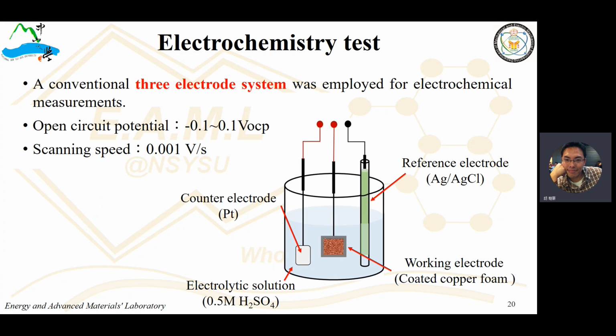Okay. And then we use the three-electrode system to measure its anti-corrosion ability. Okay, so the working electrode is the copper coated with the polysilazane pre-ceramic precursor incorporated with the fluorinated resin or other things and so on. And the counter electrode is platinum, and the reference electrode is silver chloride. And we use 0.5 molar sulfuric acid. Okay, we have a fixed scan speed.